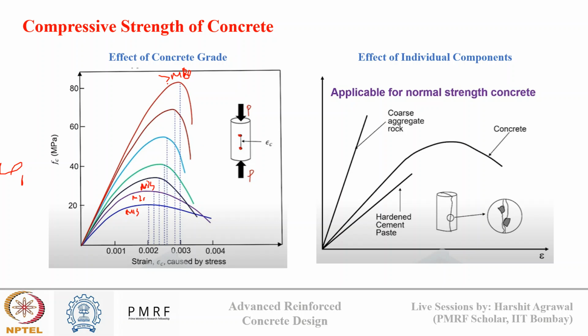However, along with this, the strain at which this peak is achieved, or we can say the deflection incurred by the concrete to reach the peak load, also increases. So if you see from this dotted line, the strain corresponding to peak is also increasing. However, if you see the post peak behavior, there is a sudden drop in strength, and this drop in strength is faster in higher grade concrete compared to lower grade concrete.